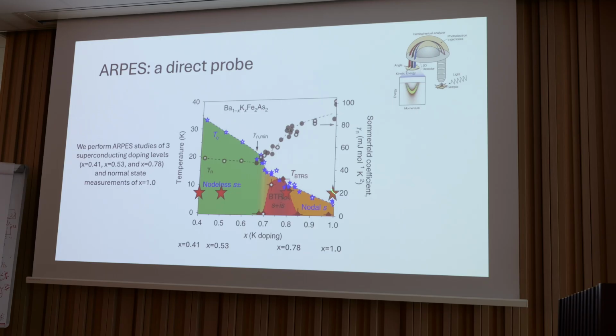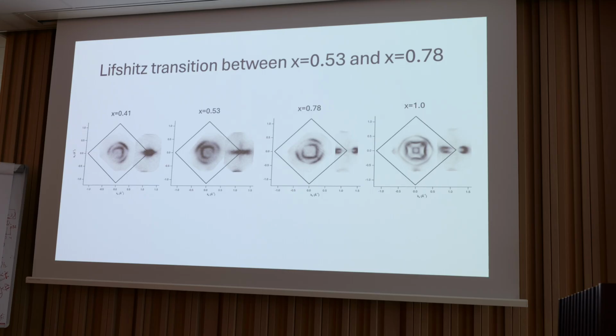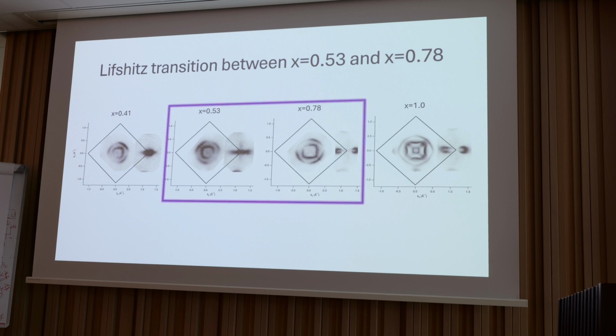And then we have one normal state measurement of the fully potassium-doped, because we can't go below the superconducting level for that. So first, these are the Fermi surfaces, just showing one of the M pockets, but there's C4 symmetry, so it's all around. So we confirmed that the Lifshitz transition occurs between 53 and 78% doping. Notably, you can see that these log-like electron pockets around M become petal-like there. So yeah, confirm the Lifshitz transition happens.